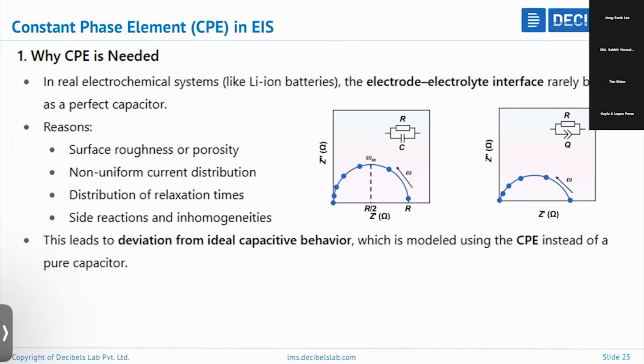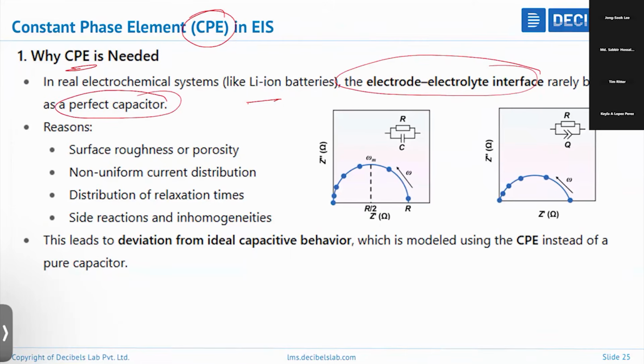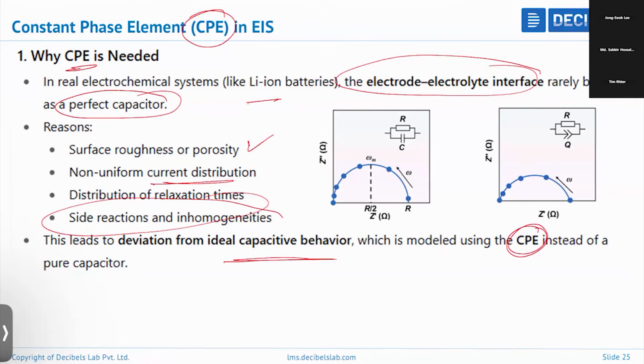So next we have one more component that is called constant phase element. Actually the capacitor is an ideal case. In real electrochemical systems like batteries, the electrode and the electrolyte rarely behave like a perfect capacitor. It is because of the surface roughness, the porosity, non-uniform current distribution, distribution of relaxation times, and also some side reactions. This leads to deviation from ideal behavior, which is modeled as constant phase element. So CPE is actually the real capacitor.